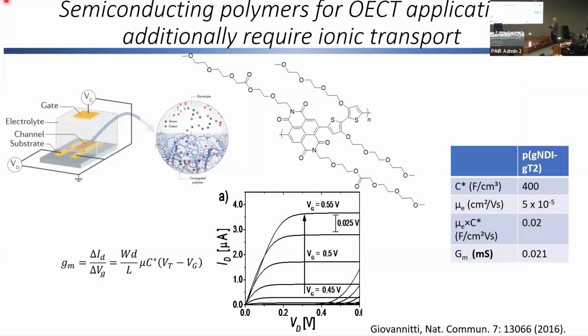in electrochemical transistors. So the difference between the transistors I've been talking about for displays and the transistors that we're now looking at here is that this is a bulk where the gate is now separated from the semiconductor, usually by an aqueous electrolyte. And in this case, we get mixed transport. So when we charge the polymer, then ions can come in from the electrolyte, you can see this here, and penetrate and compensate the charges that are injected into the polymer. So this is so-called mixed transport. Tends to be a little bit slower than for field effect transistors.